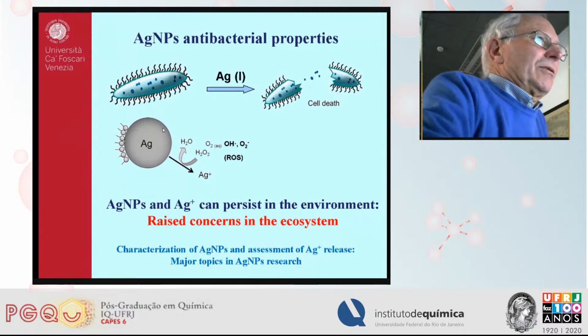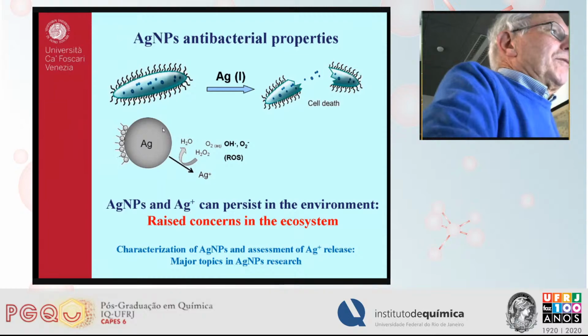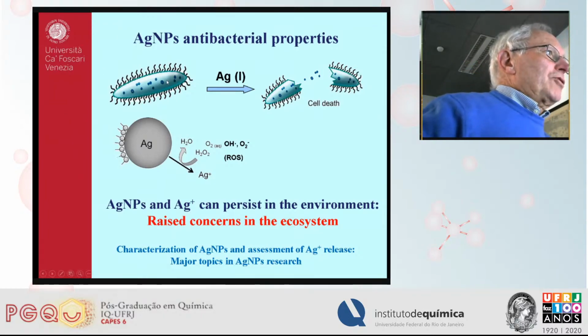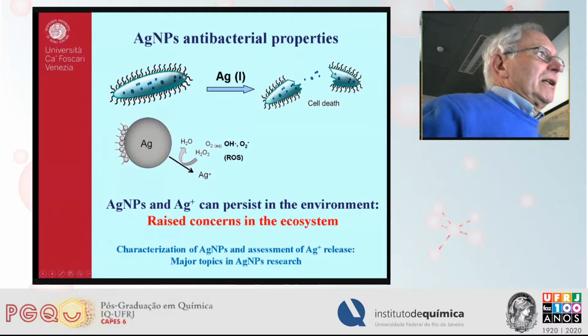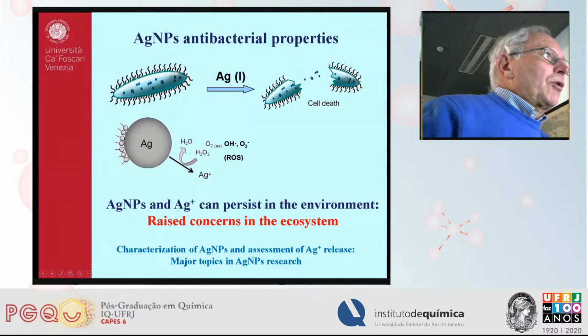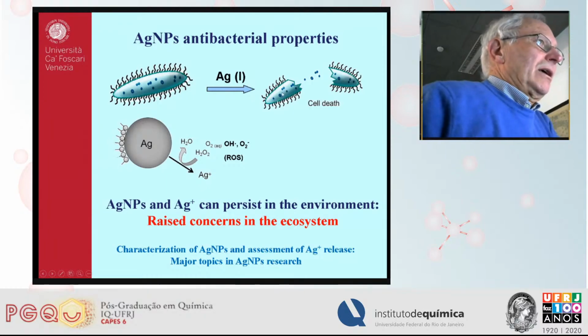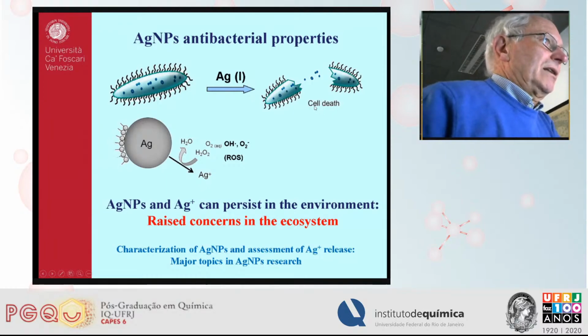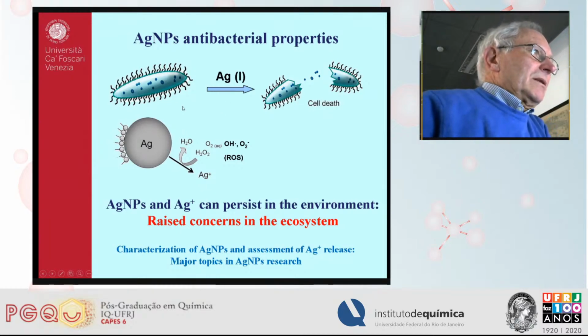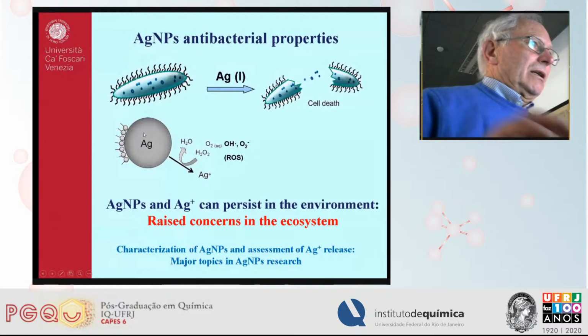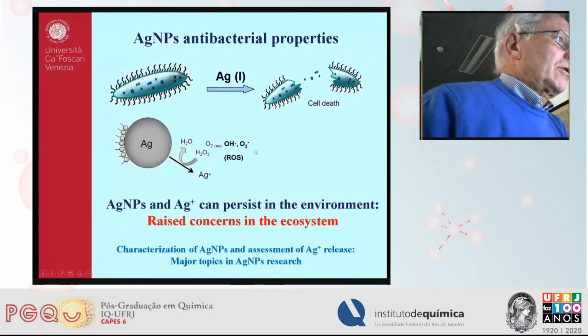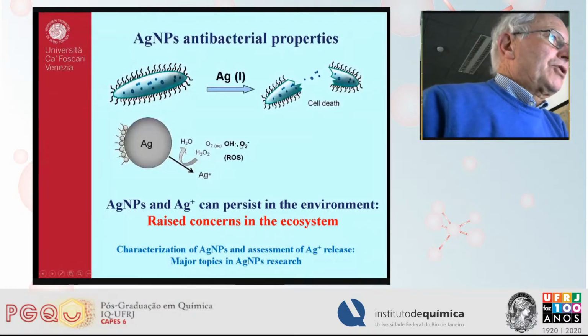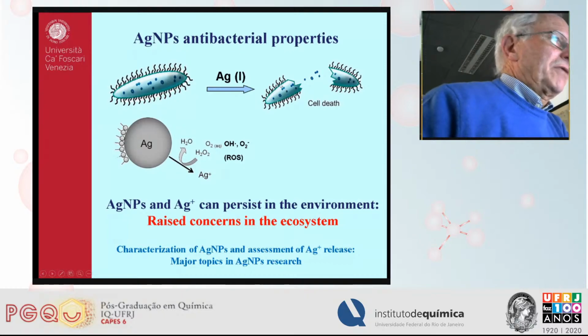The main reason for this action seems to be due to the release of silver ions, which come from the nanoparticles and bind to several moieties of the proteins of the cell membrane of the bacterium, which causes the death of the cell. But the formation of silver ion, also by spontaneous oxidation of metallic nanoparticles, also provides so-called reactive oxygen species, which are also dangerous for the life of the cell.